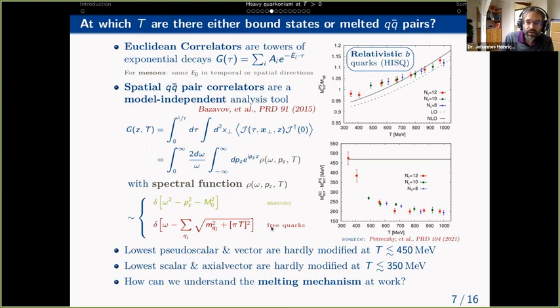So what we learn is that the ground states of pseudoscalar and vector are essentially unmodified until about 400 something MeV, while for the lowest scalar and axial vector states, we have essentially unmodified behavior up to about 300 something MeV. Now, from this, we have not used any assumptions, but we don't yet understand what the melting mechanism is, whether that is screening or whether that is dissociation.